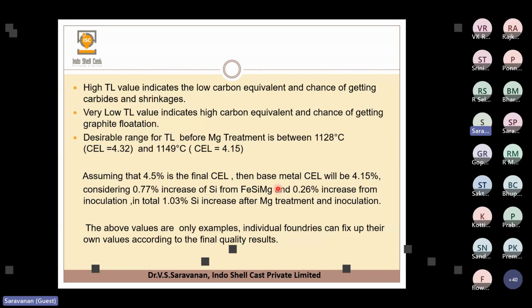So these are all the indications with TL. A high TL value indicates low carbon equivalent, and a very low TL indicates high carbon equivalent. So there is a chance of graphite flotation also. Sometimes if the graphite addition is not correct, it will again show very low TL values.